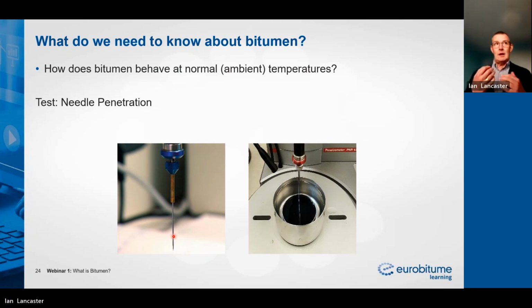So if someone talks to you about a 200 penetration bitumen, what that means is that at 25 degrees, under a load of 100 grams for 5 seconds, this needle will penetrate the surface of the bitumen for 200 tenths of a millimeter, or 20 millimeters. And that's the oldest of our bitumen tests.